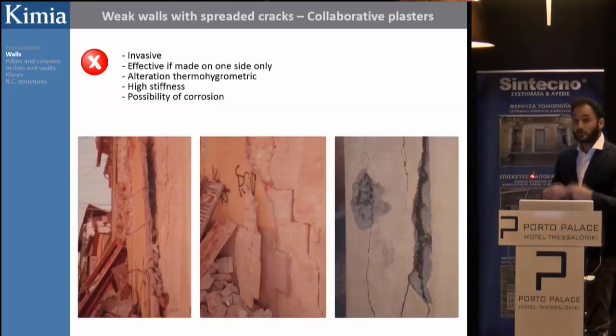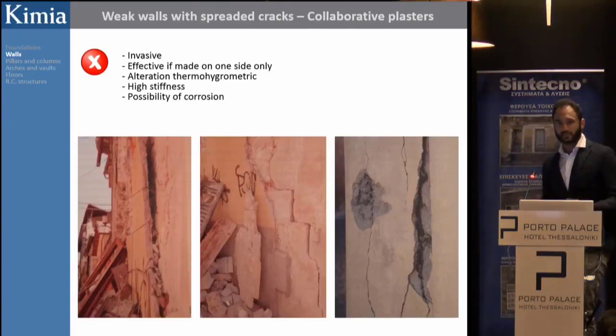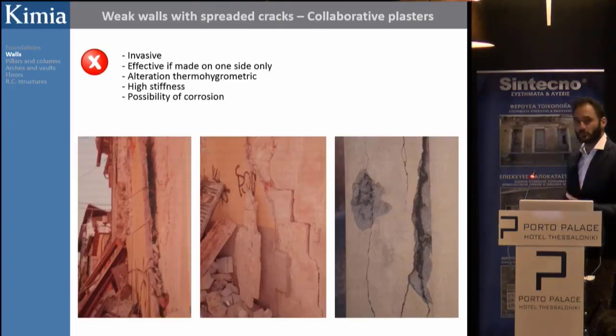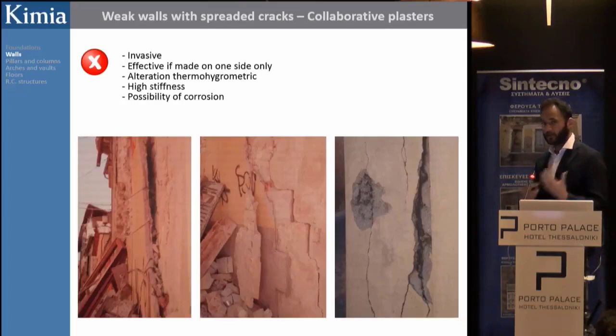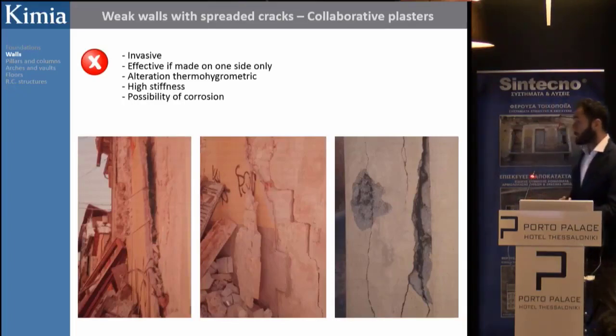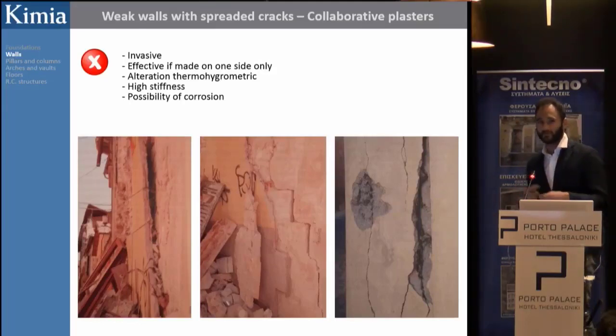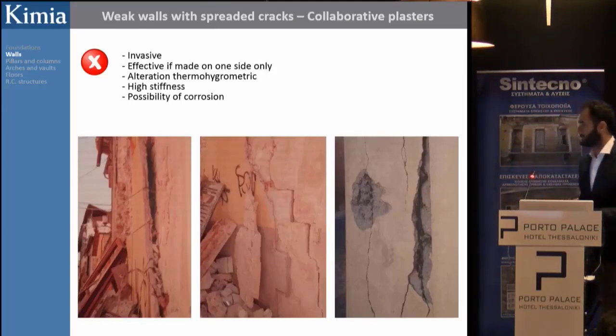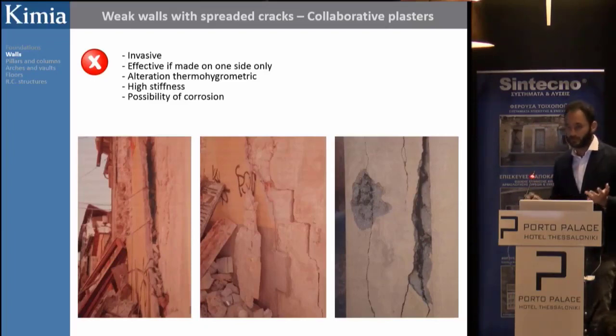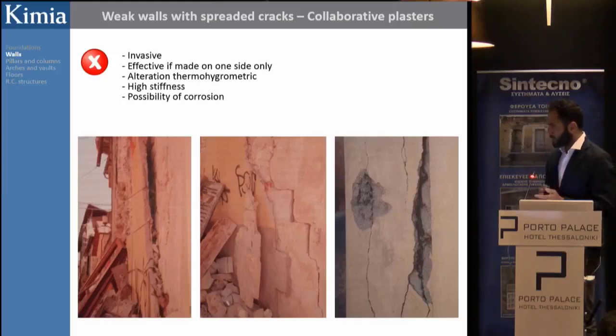An alternative option is collaborative plasters, which are reinforced with nets and connected to the substrates. Again, in the past, sometimes the idea was the stronger the better, as I said, so some cement-based plasters were used. And we obviously understood that increasing the stiffness with a plaster, which could sometimes also not be very well connected to the original masonry, wasn't a good idea.